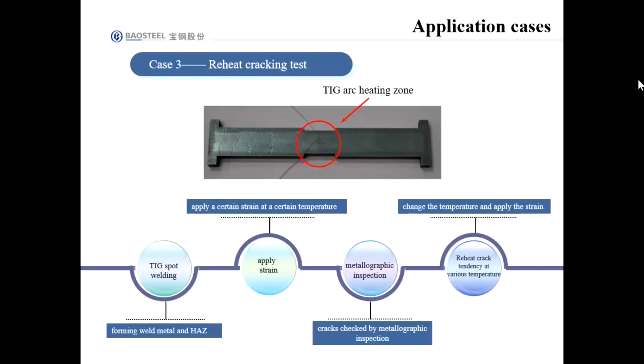Case 3 is about reheat cracking research. Reheat cracking occurs when the welded joints are reheated within a certain temperature range, such as in post-weld heat treatment. The stress-relief heat treatment is a common PWHT heat treatment. It's common for pressure vessel steels and heavy plates. Usually, a reheat crack starts in the coarse-grained heat-affected zone and ends in the fine-grained HAZ.